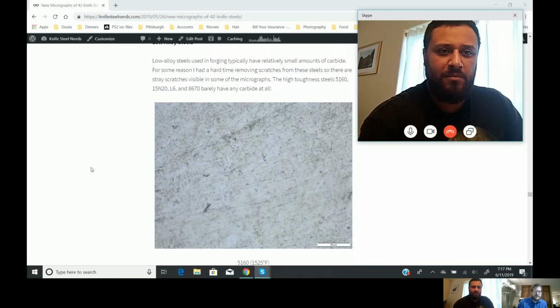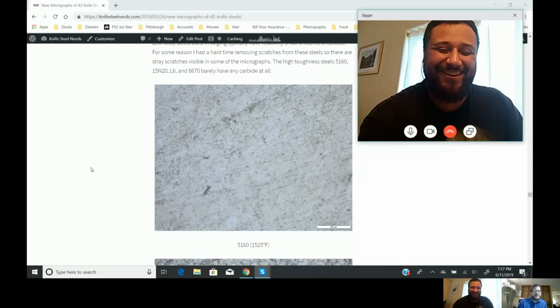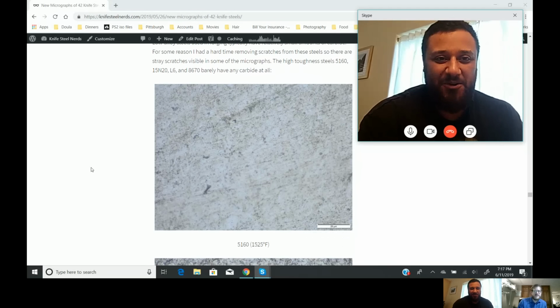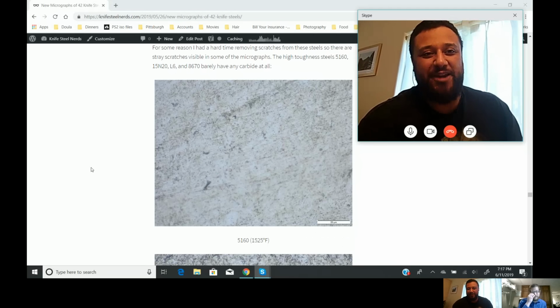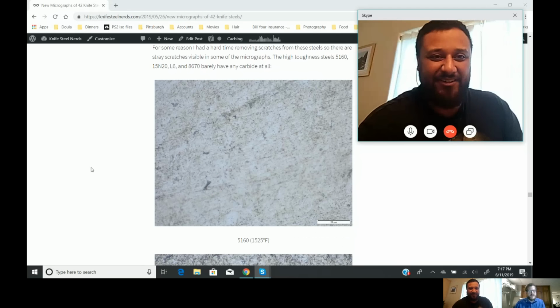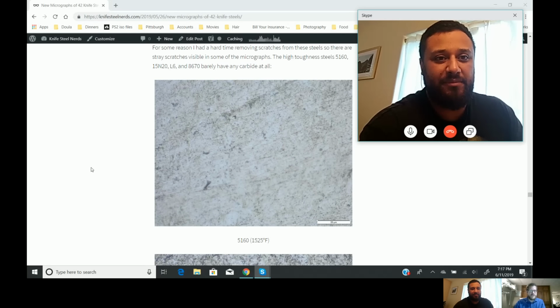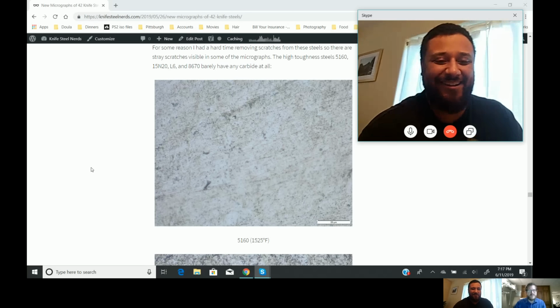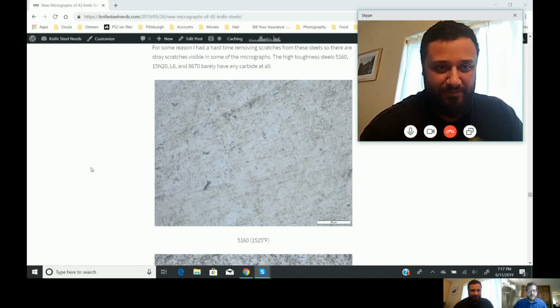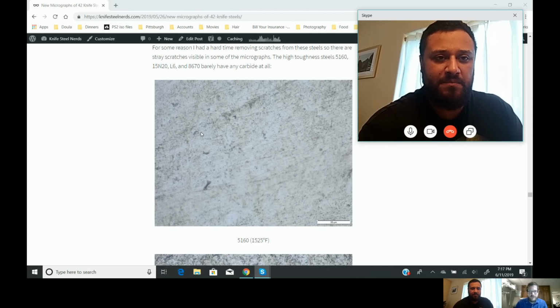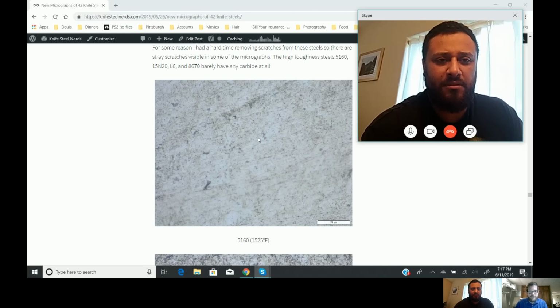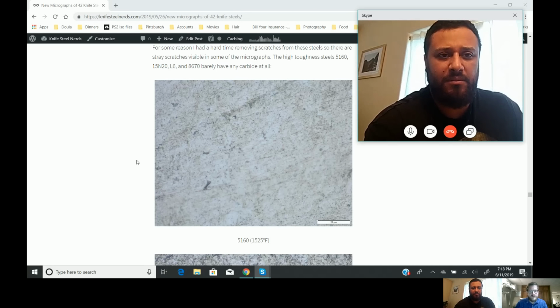Okay, let's keep moving. Now we're at the really low alloy steels. I don't see anything. You just see the scratches from my poor polishing, and that's basically all that's in there. For some reason, with the low alloy steels, I had a hard time getting rid of the scratches, but there's no carbide in 5160 that I can see. There are probably really fine carbides that weren't picked up at this magnification. You'd have to look at it with an electron microscope, but at this magnification, there's really nothing.